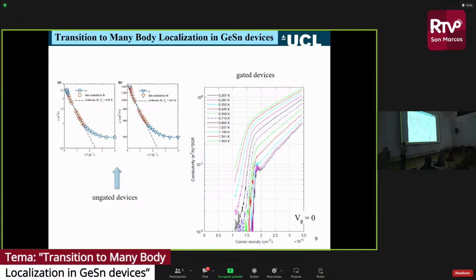So this is at higher temperatures. We see this activated conductivity. We also see this extremely sharp drop-off below about 1.5 times 10 to the 11. So this is all happening at fairly high carrier densities. As we reduce the temperature, we increase that. So the slope here changes. We're increasing that distance between the chemical potential and the mobility edge.